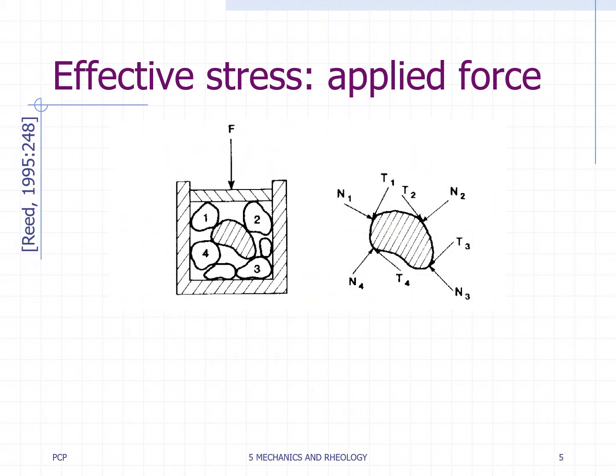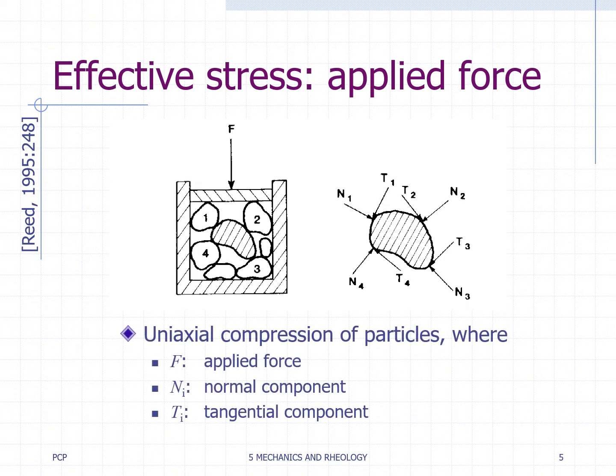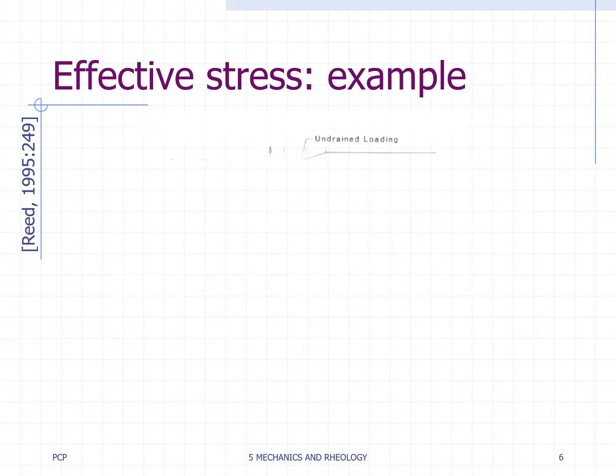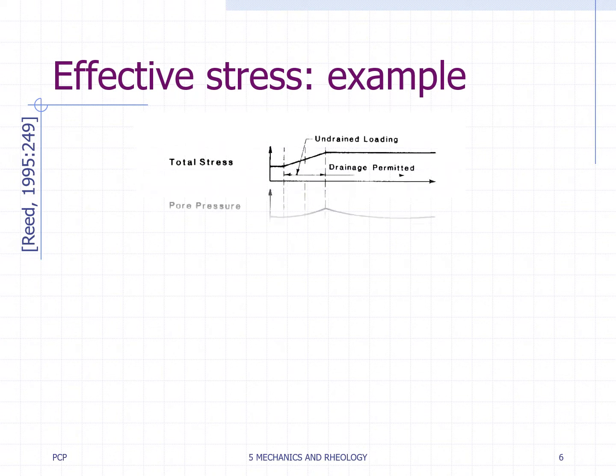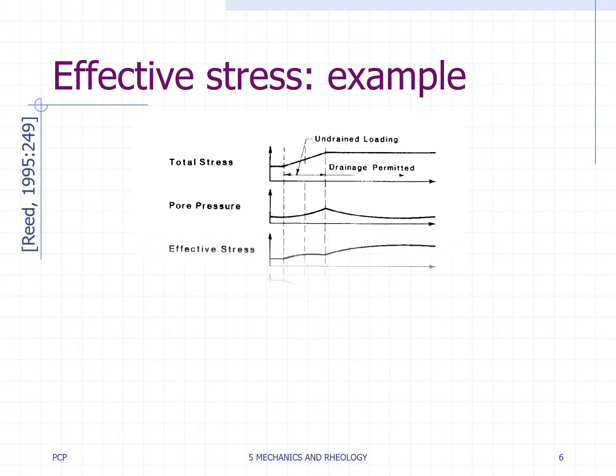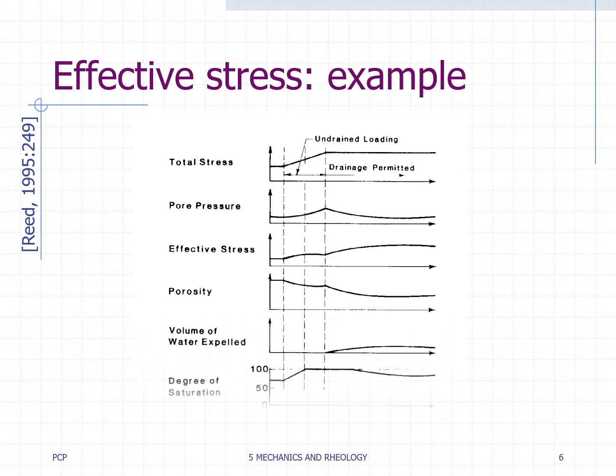Let's consider the uniaxial compression of a system of particles confined in a rigid die, as shown in this figure. The force at contacts between particles may be resolved into normal N and tangential T components. A very intense stress at a particle contact may cause local plastic deformation and fracture. The effective stress is lower when the pore phase is saturated with a relatively incompressible fluid that becomes pressurized, as is indicated in this figure. The chart shows a variation of stresses and porosity on loading a compressible, partially saturated particle system. Permeable pistons or dies may determine the effect of drainage of the pore fluid on the mechanical behavior.